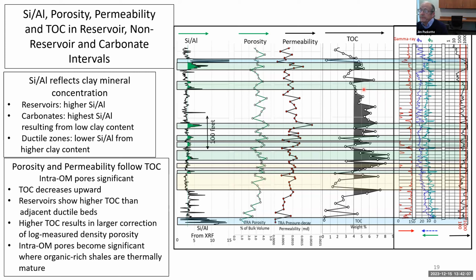Now, let's add in some tight rock analysis and some source rock analysis data. The first thing I want to point out on this panel is a silicon aluminum ratio. I've seen that used, and we developed one in this case for this particular area for the Caney, where we use an arbitrary value of something like 3 to indicate that if you have a higher silicon aluminum ratio than that, you're going to have what's colored in green. Green is for reservoir rock. And one of the things that's kind of interesting, and we see it right up here, is we see an increase in TOC, and we see an increase in permeability and an increase in porosity in this reservoir interval here.